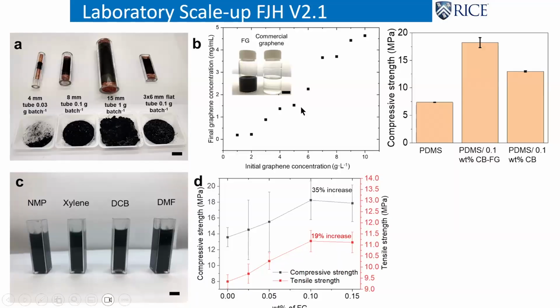You can put it in different composite materials. So in polydimethylsiloxane, you can put some of this carbon black derived flash graphene. The flash graphene came from carbon black. You add that to it and you see it doubles the compressive strength by adding 0.1 weight percent of the flash graphene. If you just do this with carbon black by itself, it doesn't go as high. So it's better in dispersing a small amount to get the strength of plastics.